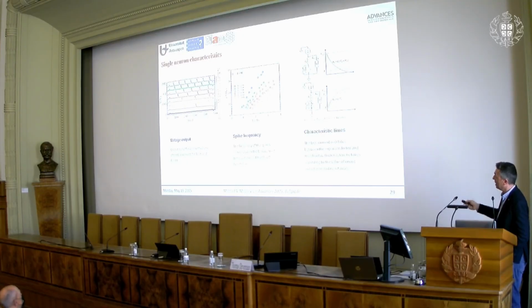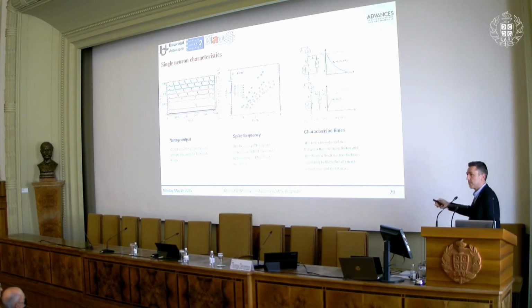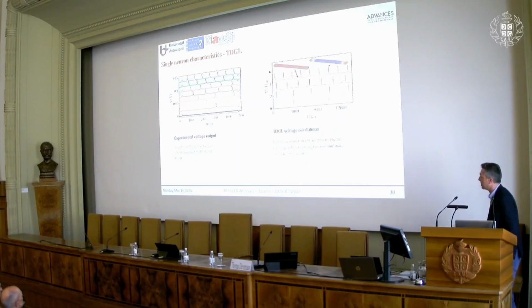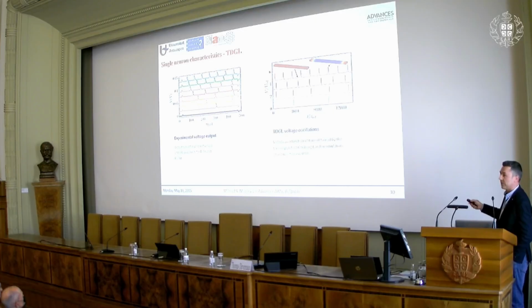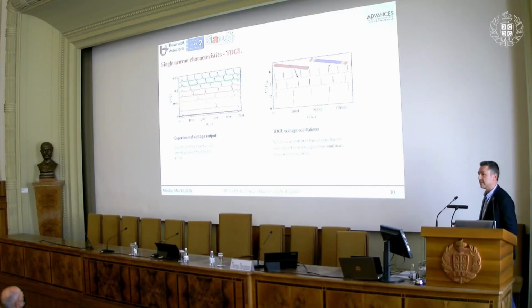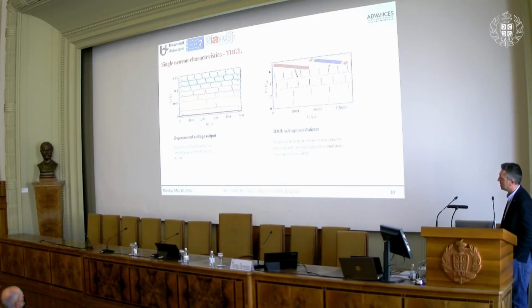As a function of temperature, we can have a dependence, and characteristic times for this rise and fall, as I said, can be controlled by the electronics. Good. So theoretically, we did the simulations and we get the exact same thing. The hotspot generated, then recovered, generated, recovered, and as we increase the current, we have exactly the same behavior with a shunt resistance. There is a shunt resistor coupled to the nanowire of a particular value. This is important.